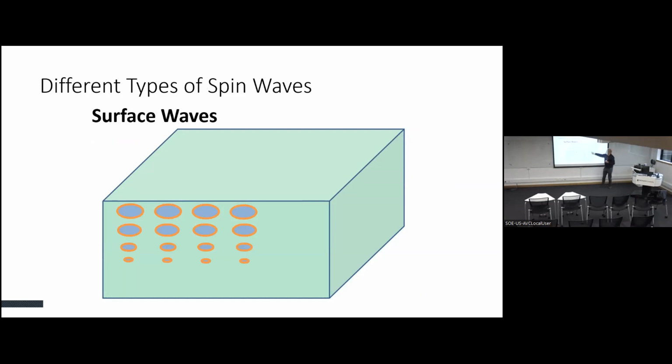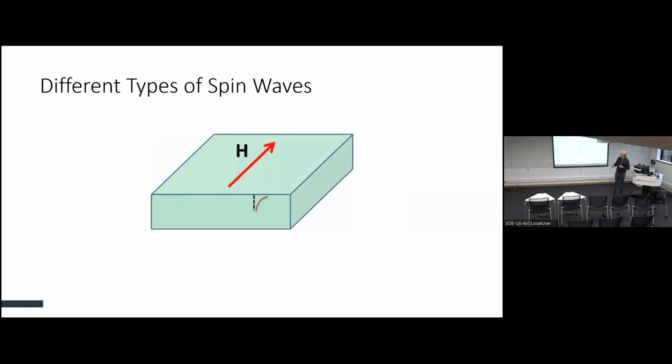So I'm going to imagine I just draw the surface wave. This is like a zero line, and the surface wave has its biggest amplitude near the surface. Great. Where does the one-handedness come in? It's here. If you have a surface wave in a film, when it goes from left to right, it's localized at the top. When it goes right to left, it's localized at the bottom. So it'll go both ways. Technically, it is reciprocal. The frequency is the same, but the localization is different.